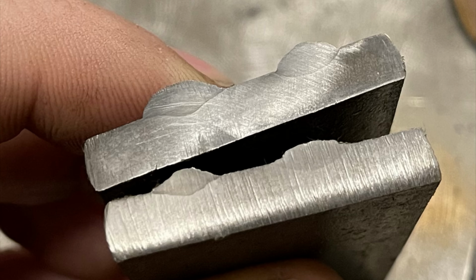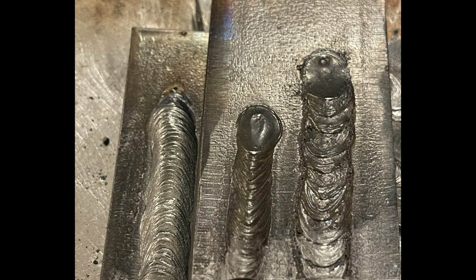After I shot this video, I thought I was selling it short by not just slowing my travel speed down and comparing it. So the welds on the left, both the top and bottom, were 7018. On the top one, I slowed my travel speed down to deposit a bigger weld, much like you run 6010 at a slower travel speed than 7018, and look at the results. Essentially, the penetration profile is identical, but there's just more weld metal sitting on top. Not ideal. Now you can see the 7018 that I ran slower is on the left. It's the same width as a 6010, but obviously the internal penetration is completely different and nowhere near as good.